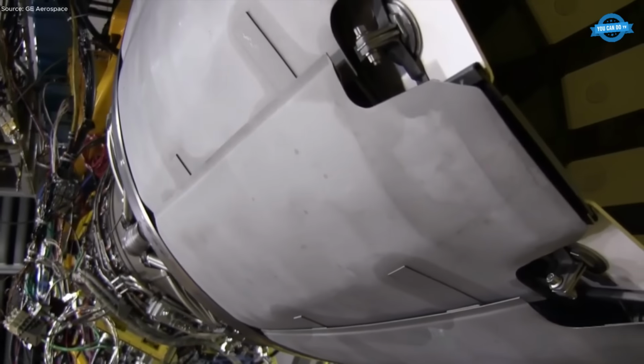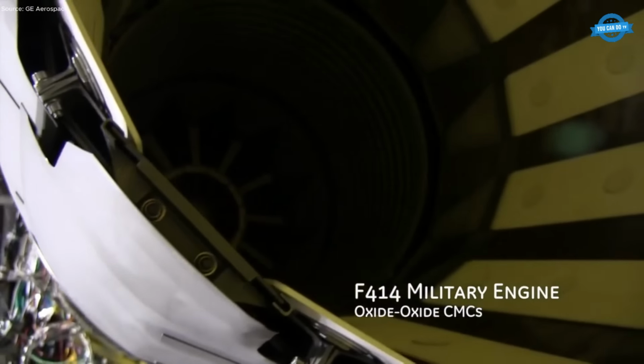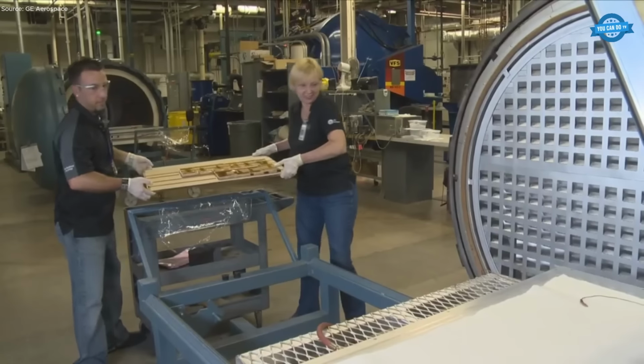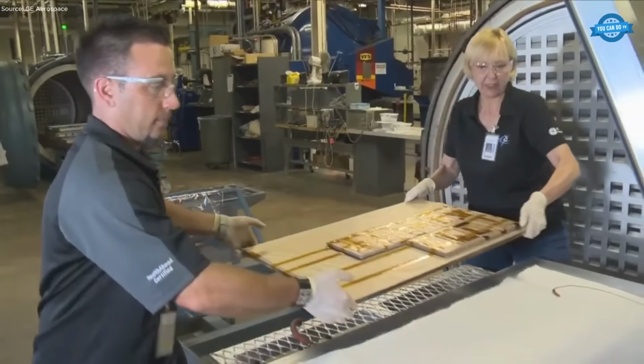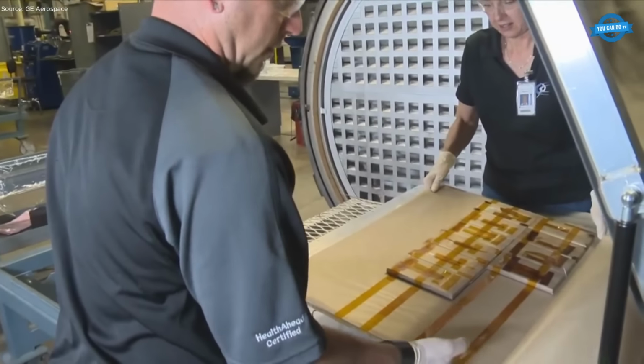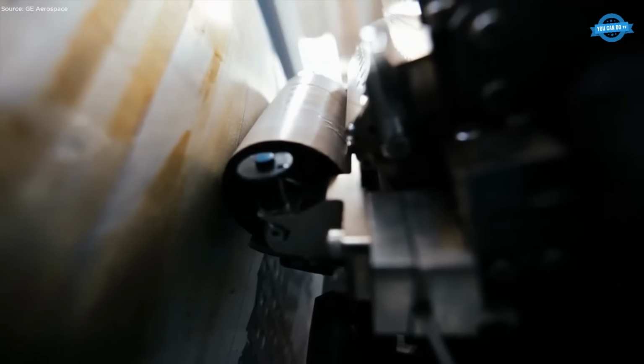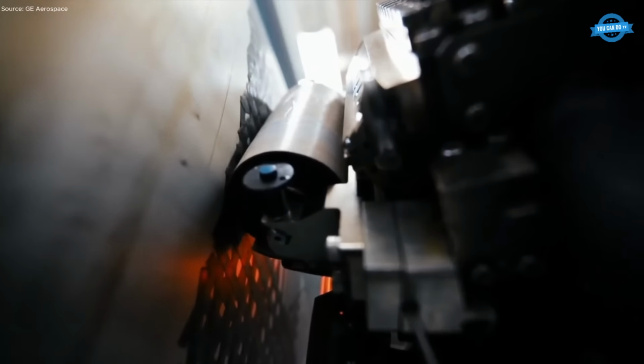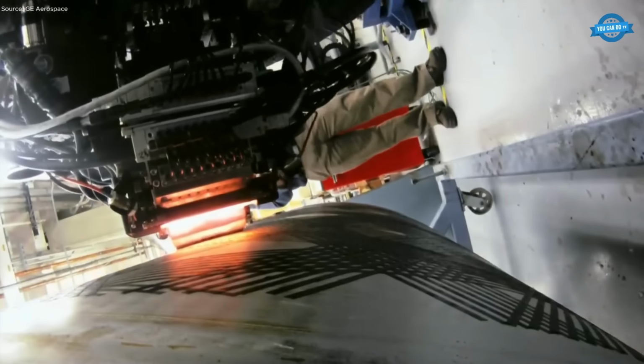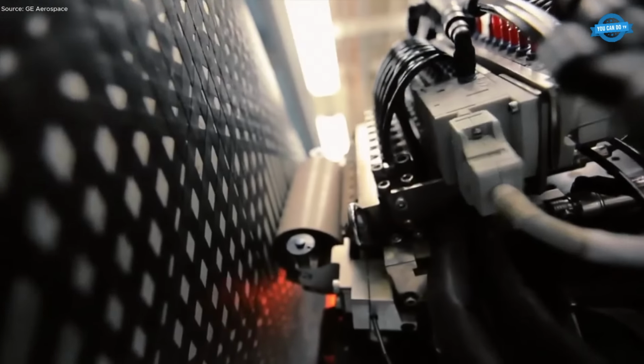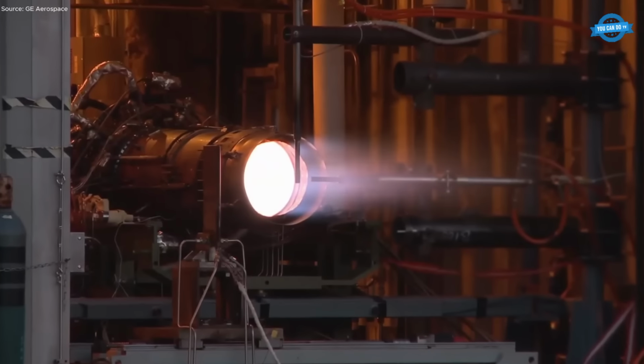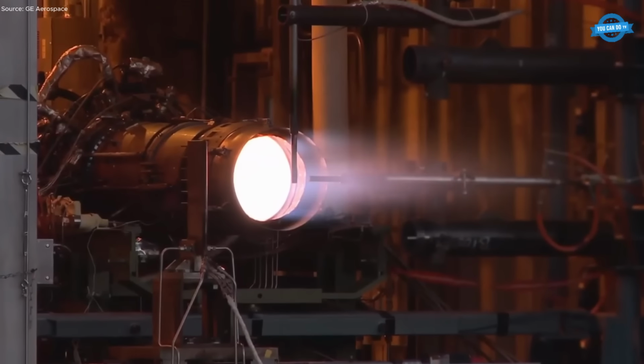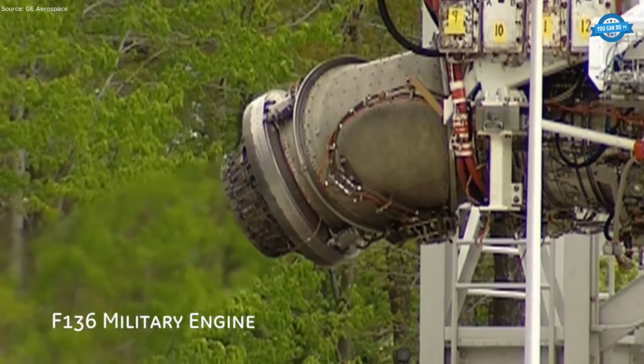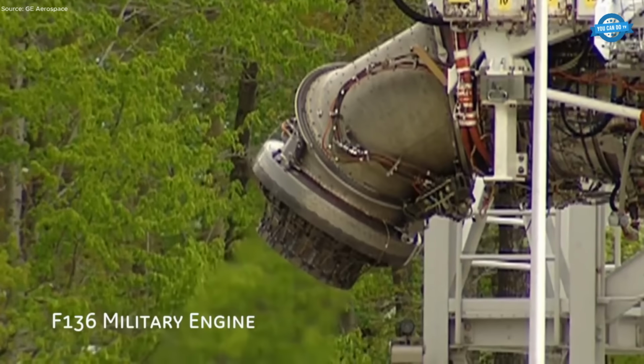Ceramic matrix composites, CMCs, are structural ceramics reinforced with continuous ceramic fibers, most commonly silicon carbide (SiC) fibers, embedded in a SiC matrix. The critical element that enables toughness is the interphase coating applied to each fiber, commonly pyrolytic carbon or BN-type layers, often proprietary. That compliant interface promotes crack deflection and fiber pullout, giving CMCs metal-like damage tolerance while retaining ceramic heat resistance.